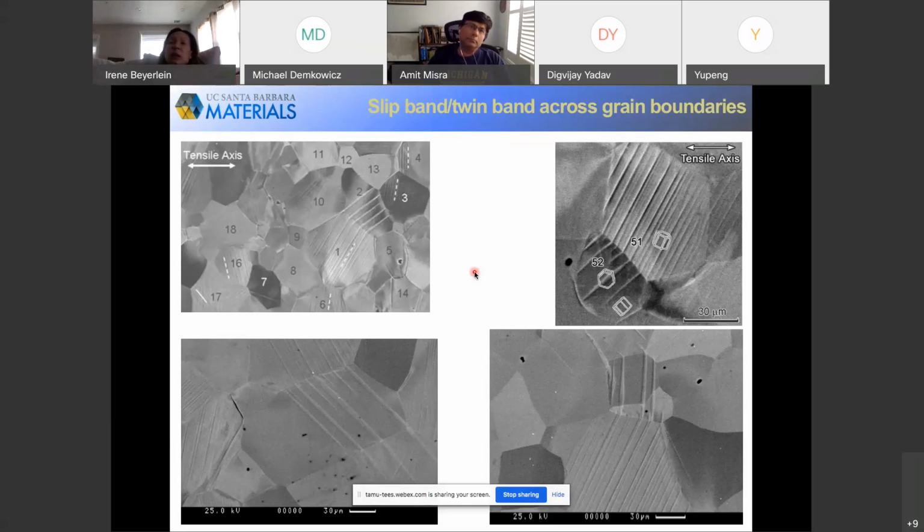So, but the further away, that interaction stress decays, and then the stress of twins far away, beyond some critical spacing, is such that it's as if they were alone. So what I'm saying is that if you were to imagine that you have twins that are embryos that are distributed, as they grow, close twins that are grown together are going to be hindered from growing. But at some point, once they reach a certain critical distance, their interaction stress decays to a point that is as if they're just growing on their own.